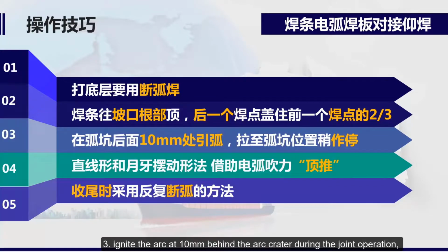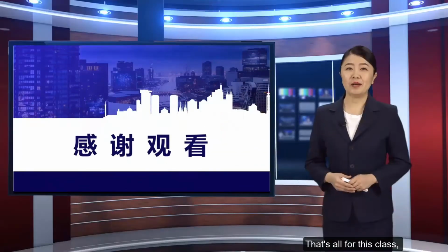3. Ignite the arc 10 mm behind the arc crater during the joint operation, and pull it to the arc crater for a short stop. 4. Use the straight line and crescent swing method to transport the rod, and use the arc blowing force of the electrode to blow the arc. When the droplet is pushed at the welding tail position, the arc should be lowered, and the arc crater should be filled by repeated arc breaking. That's all for this class.